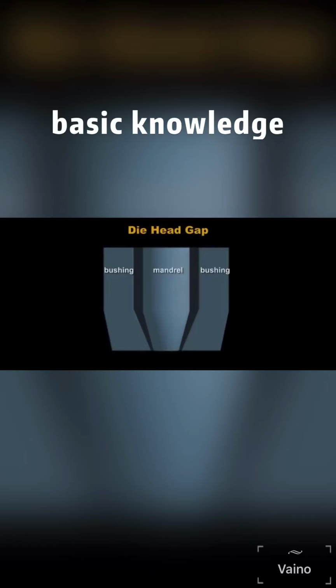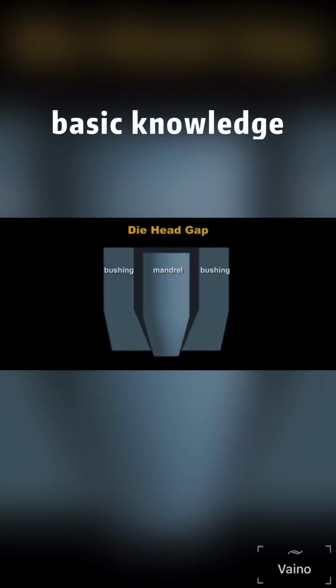In this die head design, the angle between the bushing and the mandrel are slightly different. The larger gap at the beginning of the land region reduces the pressure loss. The difference in gap thickness between the top and the bottom of the land region allows the programmer to vary the gap by moving either the bushing or the mandrel up and down while the parison is being extruded.